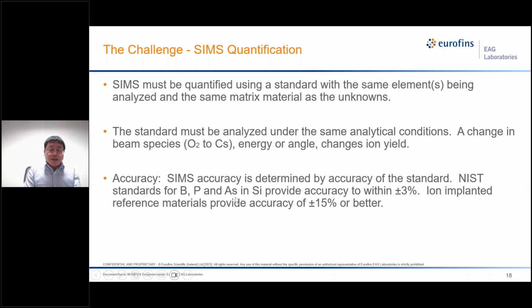NIST has standards for boron, phosphorus, arsenic in silicon, which provide accuracy of plus or minus 3%. Based on those references, we can make other implant materials. The EAG reference material will provide accuracy of plus or minus 15% or better.